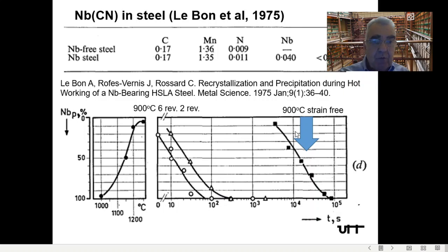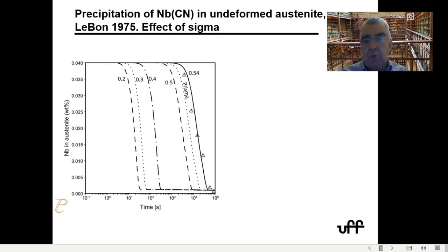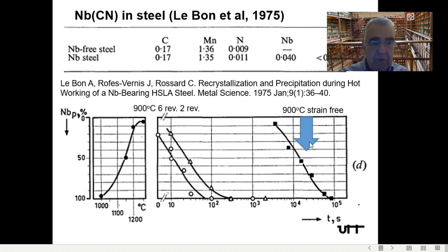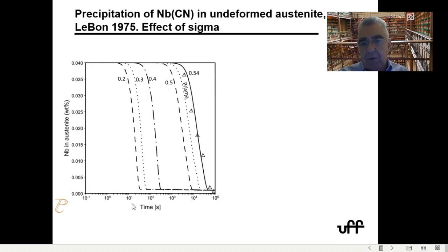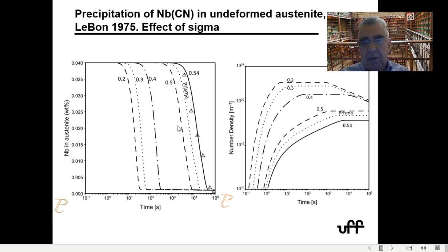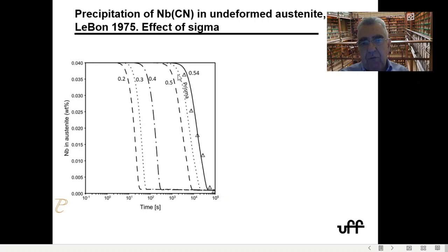So what we try to do is then we adjust this to see what happens. And then if you do it with Prisma, and these are the values, so this is exactly going back, this is this curve now, niobium in austenite versus time. And if you change the interfacial energy from 0.2, 0.3, 0.4, 0.5, 0.54, you have a huge variation in the kinetics. And the dashed line here is the value that Prisma calculates, which is fairly good agreement with the values from LeBon.